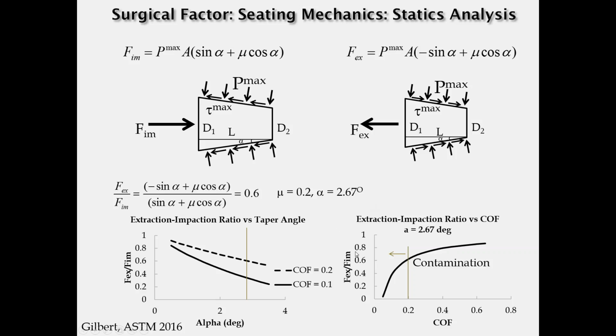The graphs I'm showing here show how that ratio of extraction to impaction varies with things like the taper angle as well as the coefficient of friction. And importantly, you can see that when your coefficient of friction of the engagement drops well below 0.2, that your ratio falls away quite rapidly. And so if you have contamination or other factors that are reducing the coefficient of friction at that junction, then you can see a loosening of that component relatively easily.